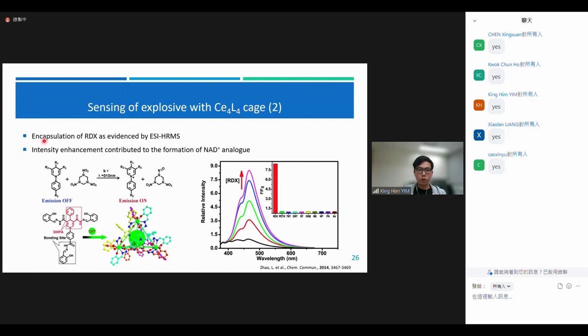So the encapsulation of RDX, although it's already confirmed by HRMS, they want to know whether the emission intensity is affected by this encapsulation. As you can see on the left-hand side, the emission initially is off, but upon the addition of the RDX, it becomes a turn-on sensor. And the right-hand side shows the change in the fluorescence spectrum upon addition of RDX, and the radiative emission intensity increases.